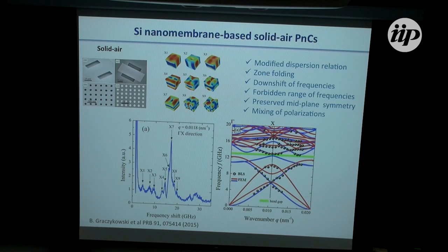So we now take a look at the holey ones, or the solid air. Brillouin scattering showed us a rich set of peaks, which can be all placed in the dispersion relation. It shows very clear, it's amazing, the agreement here. We have a description of the symmetry of these peaks, that is to say, we know how the amplitudes of the displacements look like around holes for a particular mode.